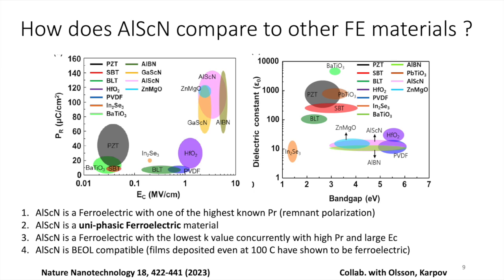The other interesting thing over here, if you look at the right-hand side graph, is that it is a material with a much lower dielectric constant, a low dielectric constant together with a large band gap as a ferroelectric material. And this makes it very suitable for low energy charging and discharging. Many times in ferroelectrics, such as the oxide ferroelectrics like PZT or SBT, which are mentioned on the upper side of the right-hand side graph, the dielectric constant values are so large that you have to expend a large amount of energy just to charge the material to then switch it. But if the dielectric constant is small, you don't have to spend as much energy to charge the material in order to switch it. So this is quite valuable in terms of low energy operation.